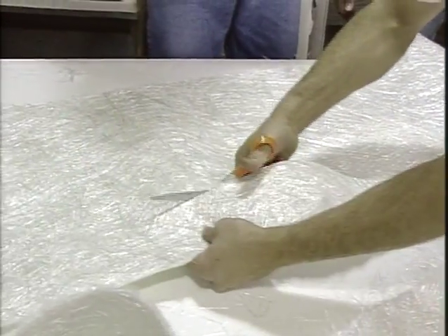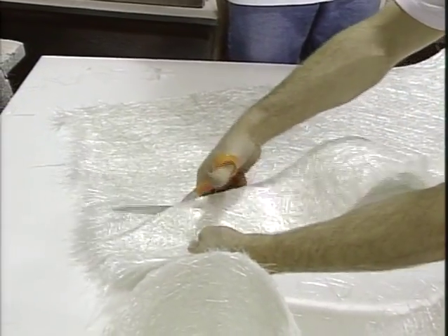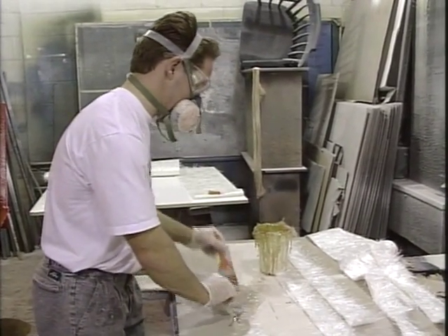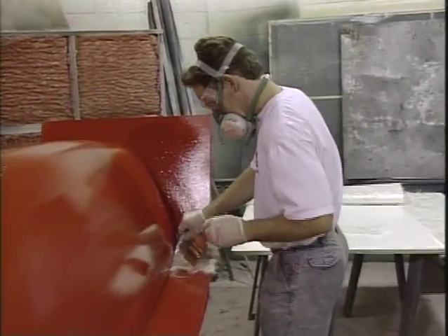To eliminate air pockets in the corner where the flange meets the plug, we pre-cut strips of mat in 2 sizes. We cut 6-inch wide strips of mat which match the width of the exposed flange. These strips can be laid into place easily and have nice cut edges on both sides. Thoroughly saturate the strip of mat you intend to lay on the flange. We don't particularly care about the weight of the mold and are fairly generous with the resin content.